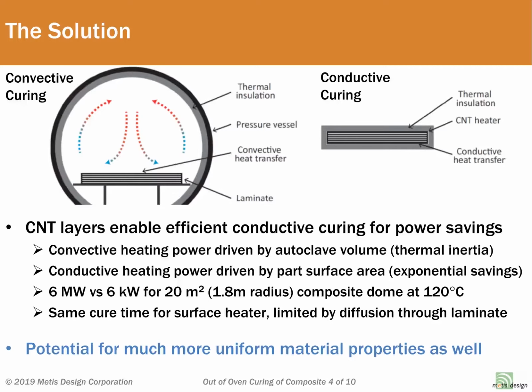Traditionally, composite components are cured convectively inside of an autoclave. An autoclave is a pressure vessel that serves two purposes. First, to act as an oven to heat the polymer resin inside of a composite prepreg. Second, to apply 100 to 200 psi of pressure to consolidate the plies in a composite laminate to eliminate voids due to trapped air. While autoclave curing has been the gold standard for fabricating aerospace-grade composite components, it is quite energy